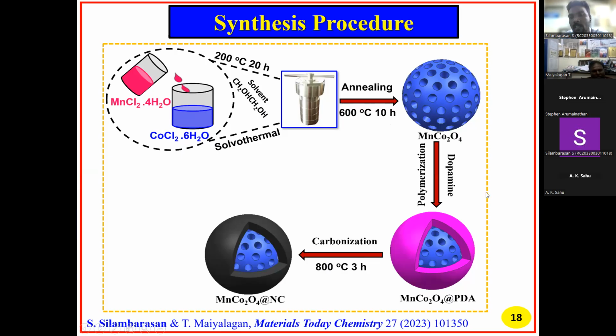After that, it is composited with dopamine in three variations, which we prepared as 1:1 ratio, 1:2 ratio and 2:1 ratio. Then the prepared material is carbonized at 800 degrees C for 3 hours, and finally we got the core-shell structure like MnCo2O4 at nitrogen doped carbon.